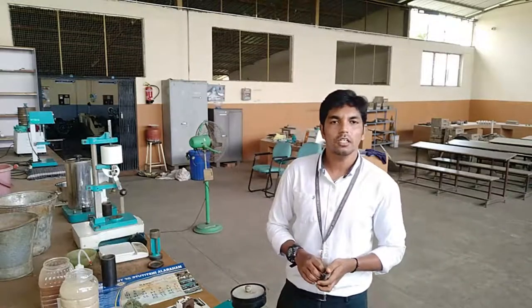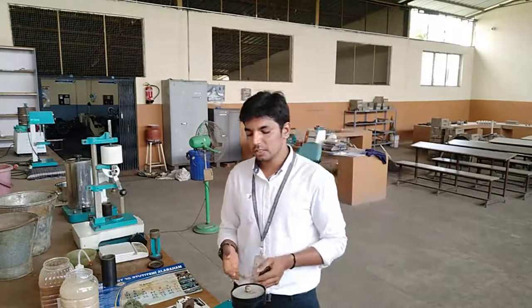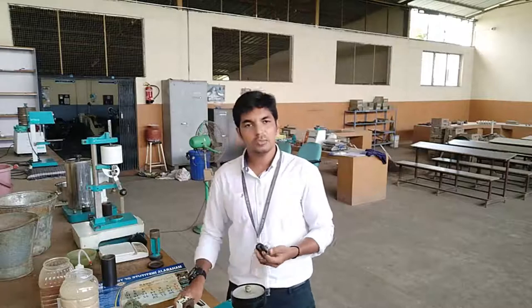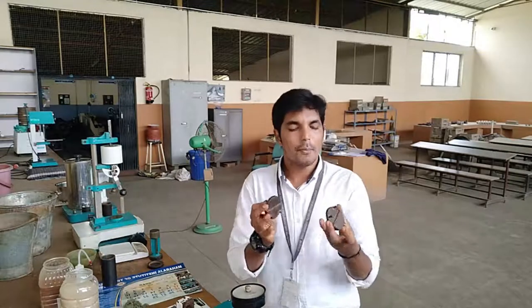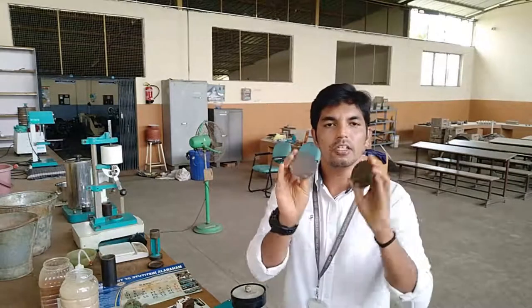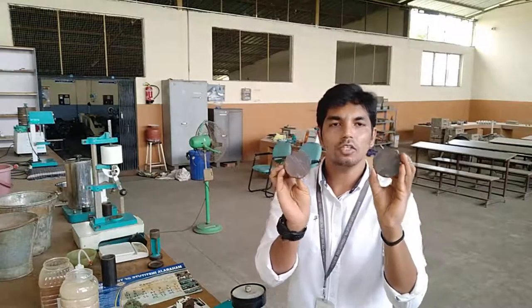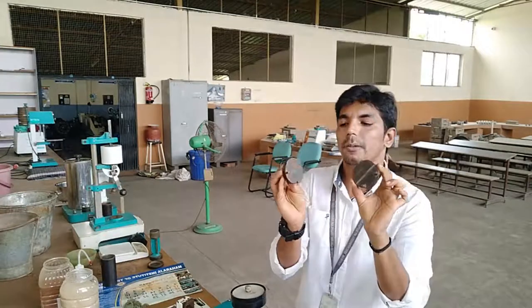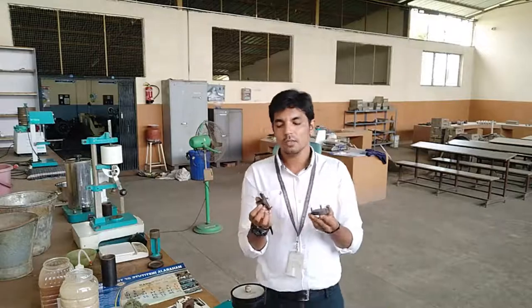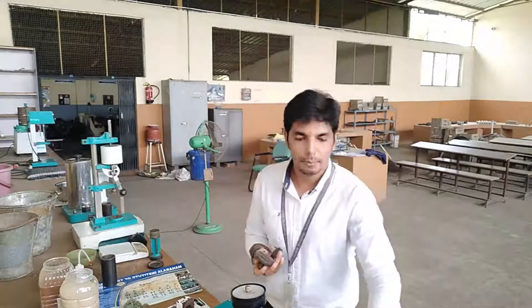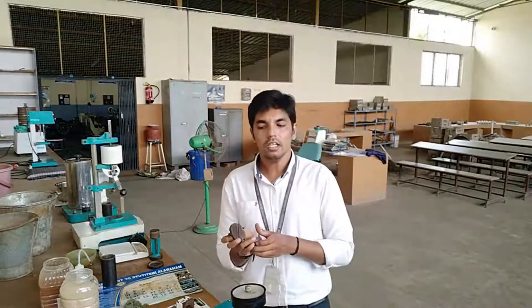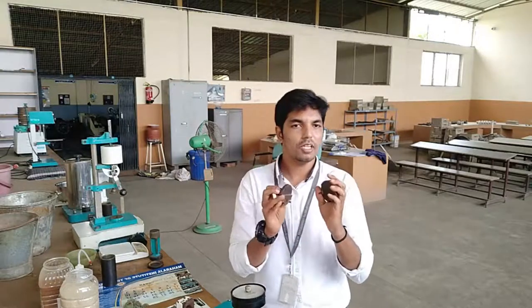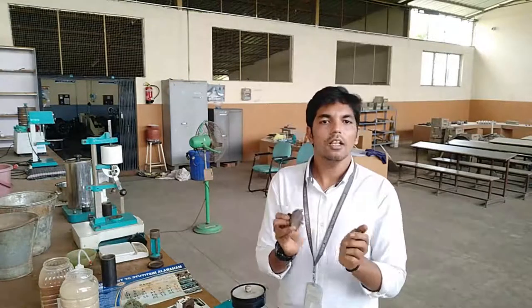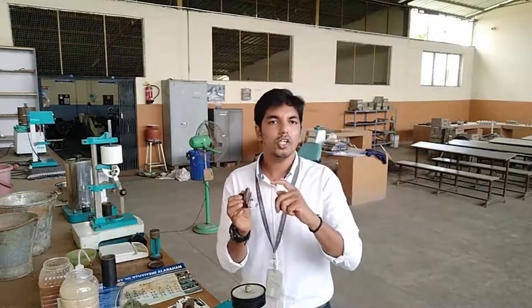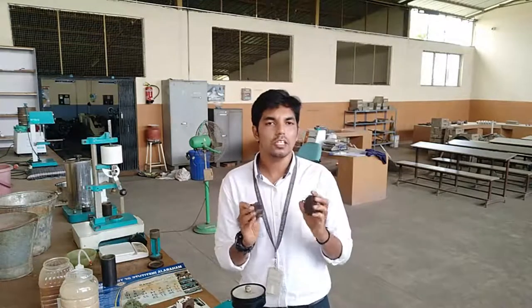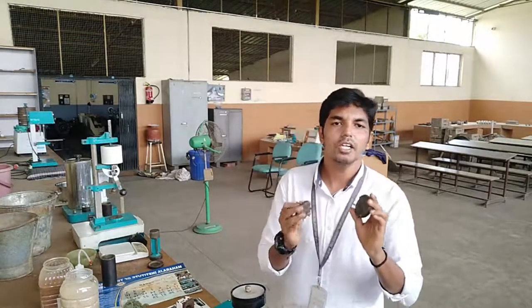In this experiment, initially we need to prepare the sand specimen of 50 mm height and 50 mm diameter. After preparation, we need to place the specimen between the pressure pads of the shear test. Observe the main specialty of these pressure pads: after applying the compressive force through this hand wheel, the specimen will first undergo shear failure. Later, the specimen will undergo compressive failure, which is very important in the shear test.